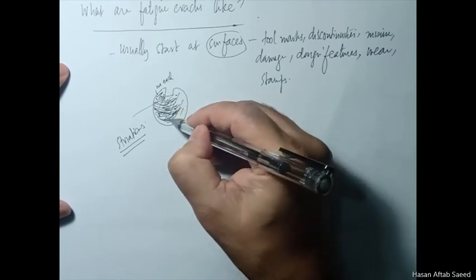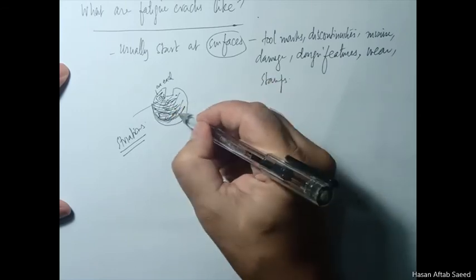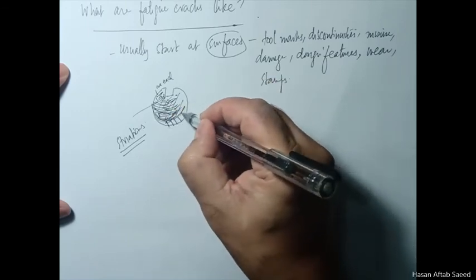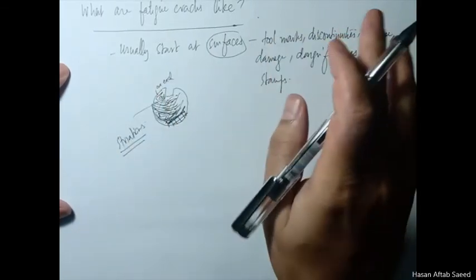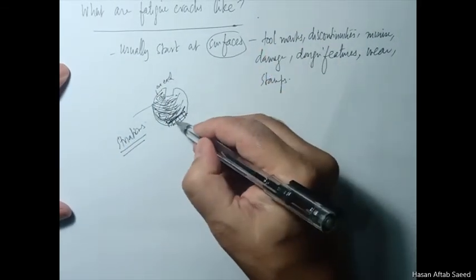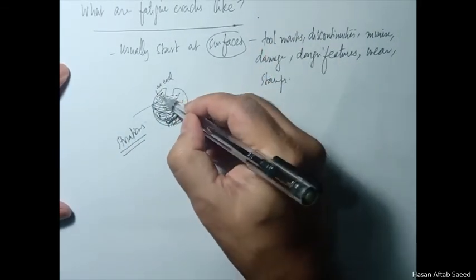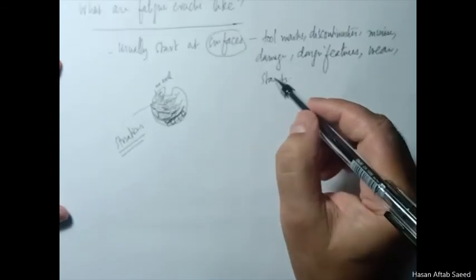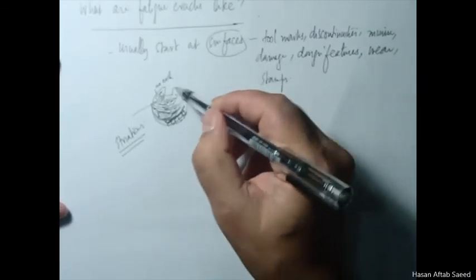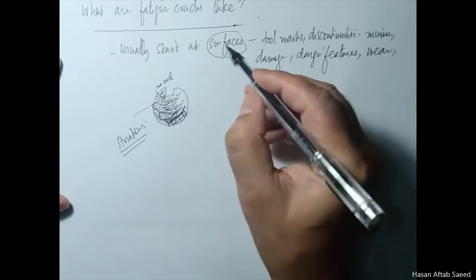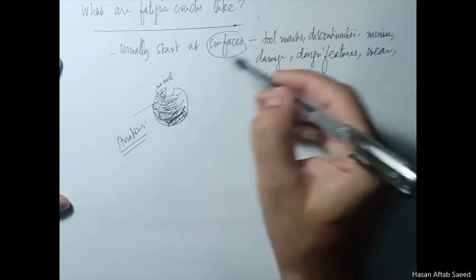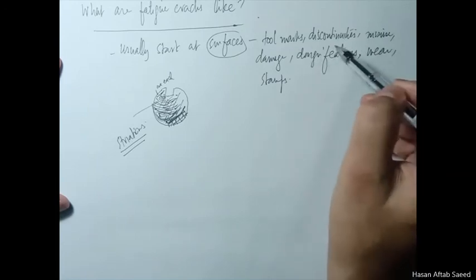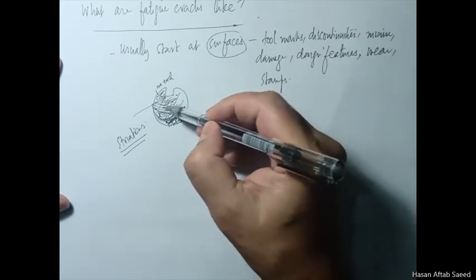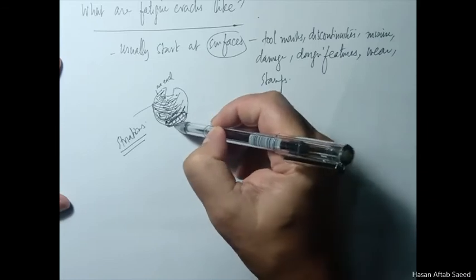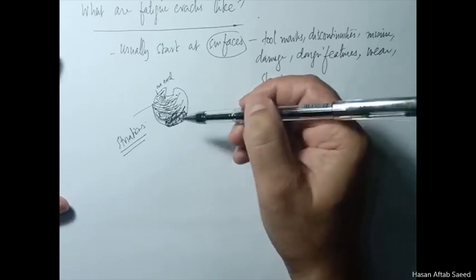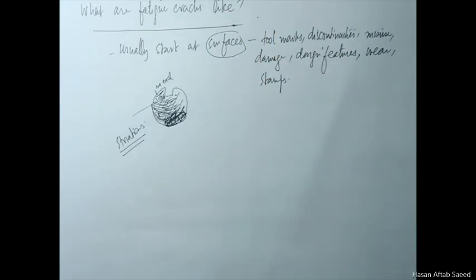At a certain time critical crack length will be achieved, and in the remaining part there will be no striations here. It will just break in one go. So it will be very clean here. It's clean also here, but there will be striations here. So this kind of a crack will start from the surface, some sort of surface tool mark or discontinuity or something like that, and then it'll keep on increasing. There will be striations, and the remaining part it will just break in one go. There will be no striations here. So it is very easy to identify a fatigue crack.